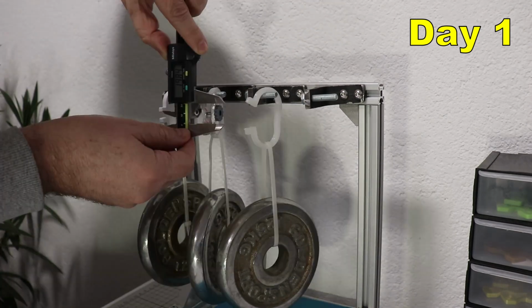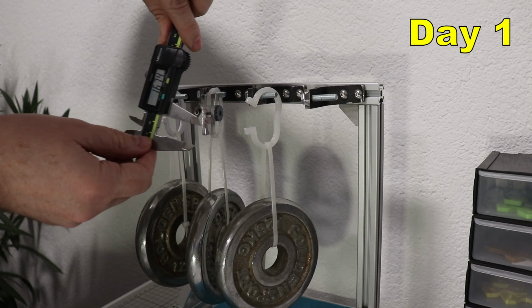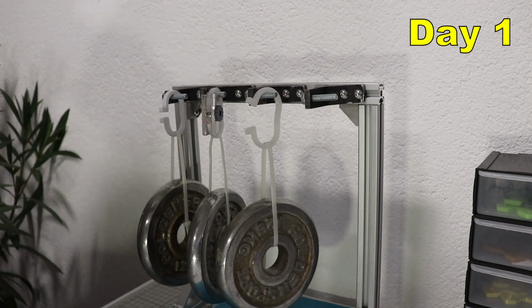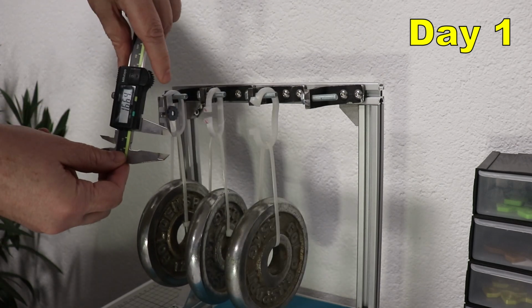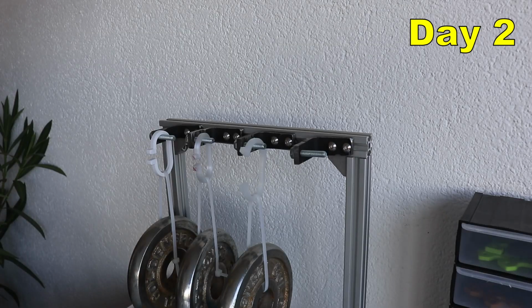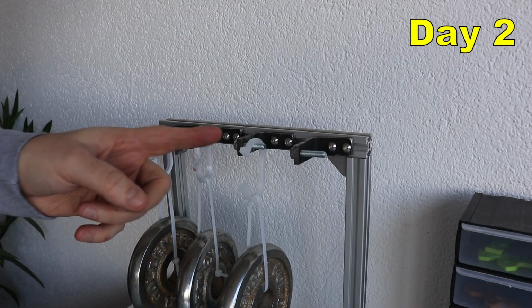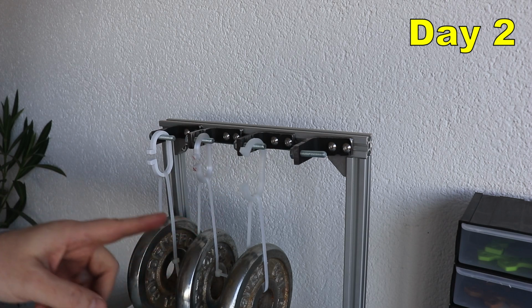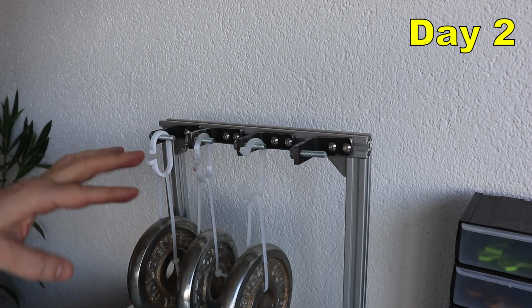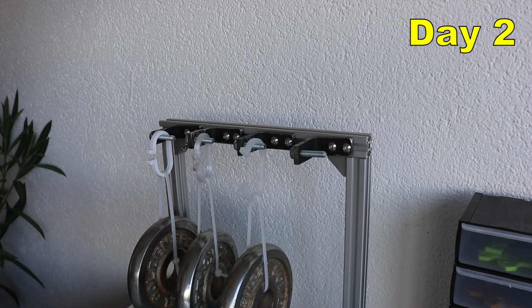33.76, 16.74, 16.64. And after 2 days I can see that the nylon is continuously creeping, while for the polycarbonate and ABS, visually I cannot see a big difference.